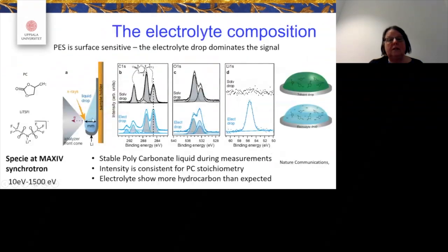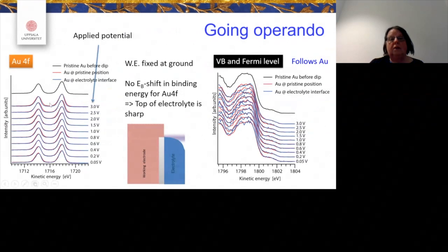Try to look at, for instance, electrolyte drops and try to see what kind of surface effect we have between the liquefied drop and, in this case, a lithium metal, and see that the components close to the lithium surface are actually different from the components on the surface of the droplets. That came out in Nature Communications last year, and so I think that's interesting. And we are actually trying to do the first electrochemistry, and it's not so easy to see anything in these plots yet, but we now have data that we have just sent in for publication that we hope might be very appreciated by the scientific community.